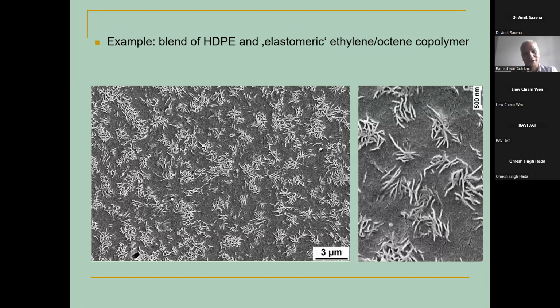One beautiful example of imaging a polymer blend with scanning electron microscopy in the SE mode, secondary electron mode. This is a polyethylene, if you remember before, I was talking about high density polyethylene and very low density polyethylene. A very similar substance it is. High density polyethylene with ethylene octene copolymer, which is structurally very similar to high density polyethylene, but it has many small branches. This is a low magnification image, and this is a high magnification image. Scale bar is here, scale bar is here.